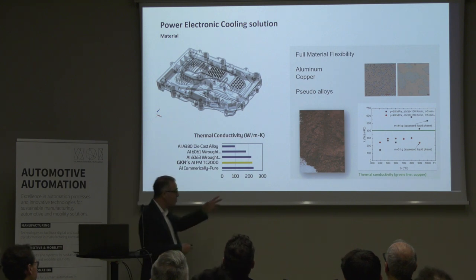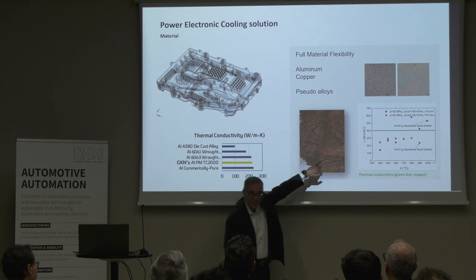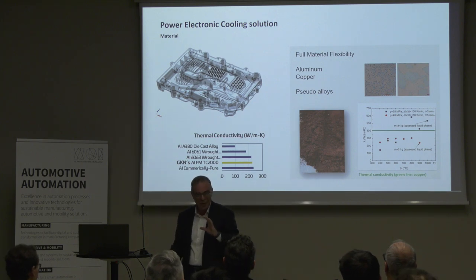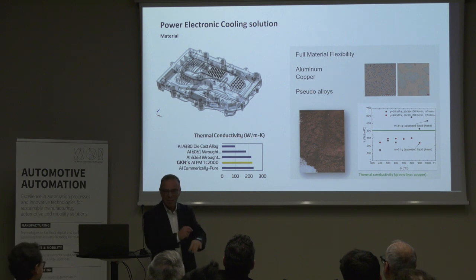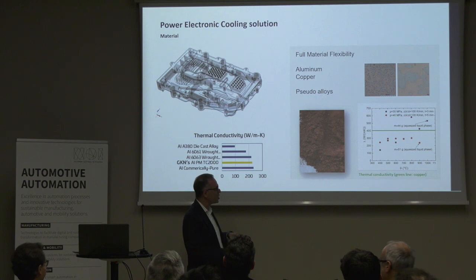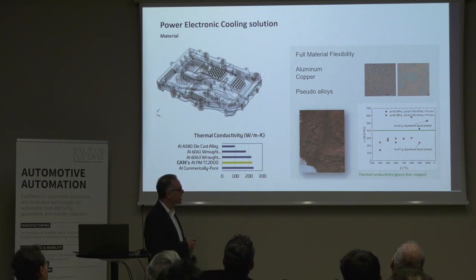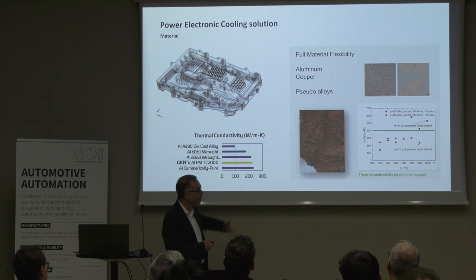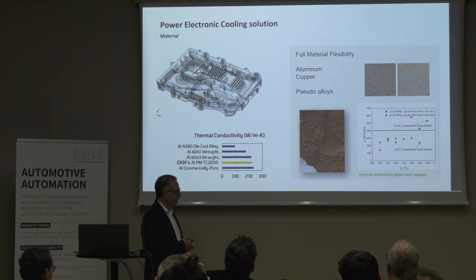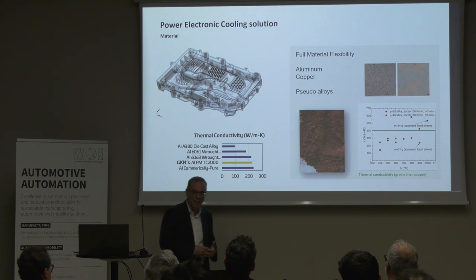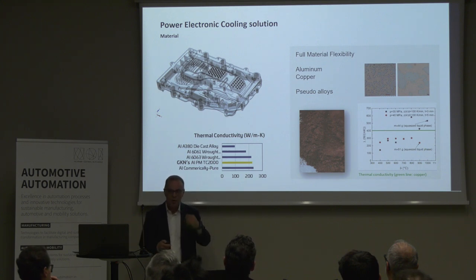You can see this is copper powder. These small white spots are synthetic diamonds, okay? So it's not the diamond for the ring and everything. It's a little bit cheaper, but not so much cheaper. And the green line is 400 watt per meter Kelvin. That's the conductivity of copper. And we are far above, so we could reach almost 550 with this quite expensive material. This is just to give you a flavor of how our technology can contribute to the big topic of thermal management in battery cars.